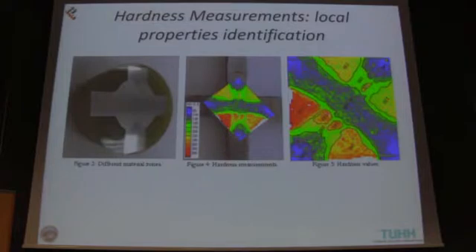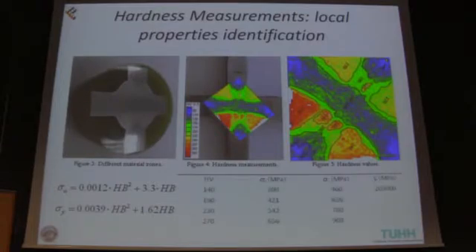Here we see the test. We see the polished specimen, and we can also see already here the different material zones. In the other figures, we see a whole map of the hardness measurements. And on the right figure, we see that we ordered the hardness values in groups. Using these groups, we related the hardness values to the ultimate and the yielding stress of the material. These two equations were taken from literature, from a recent paper of Lopez and Fatemi. Using these equations, we define the different material characteristics that we are going to use.